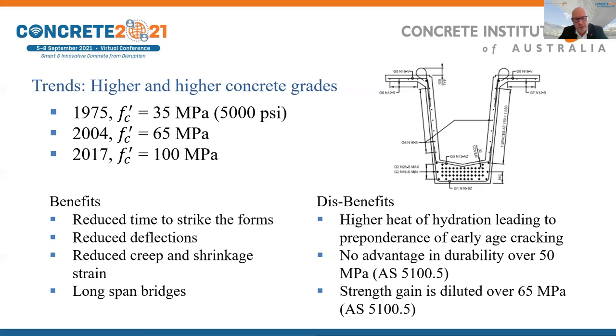Under the 2017 Australian Bridge Standard, there's no advantage in specifying concrete over 50 MPa for durability. And even for strength, the strength gain is diluted for strengths over 65 MPa. So think twice before automatically going to those higher strengths.